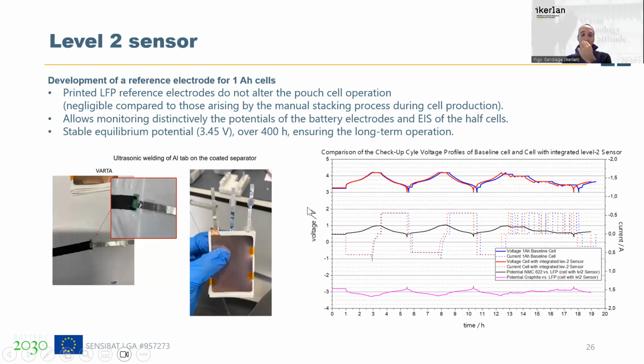and we also did some tests to measure if something inside the cell has changed. Apparently, we can also detect a small increase in internal resistance of the cell. So this electrode somehow affected the behavior of the cell. But we also did aging tests, and we can assure that this increase of internal resistance and this third electrode did not affect the long-term behavior of the cell.